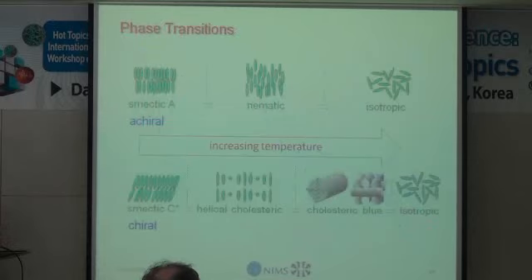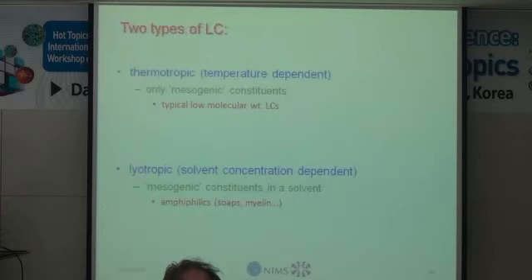And in between these phases, there are phase transitions. So if you start at, say, with a smectic A phase at low temperature, when you heat it up, there's a phase transition into the nematic phase, and then another phase transition at some well-defined temperature to the isotropic liquid. And the same thing is true with the chiral materials as well. And finally, there are two types of liquid crystals, and this is really mainly for a historical distinction. There are materials whose phase behavior depends primarily on temperature. These are called thermotropic. And others where the phase behavior depends on concentration of a solvent, and these are called lyotropic ones. So these are essentially soap-type materials. So this is not so accurate because these depend on the presence of solvents as well, and these depend on temperature, but for historical reasons this distinction is there.